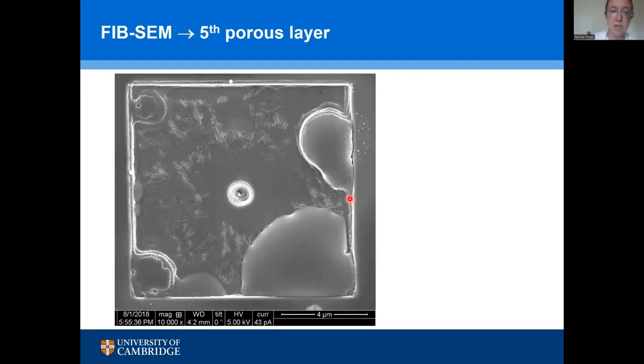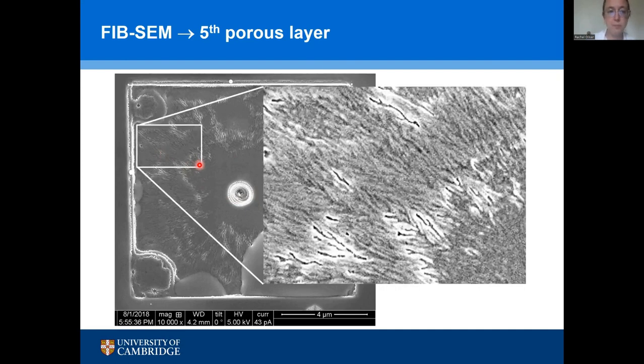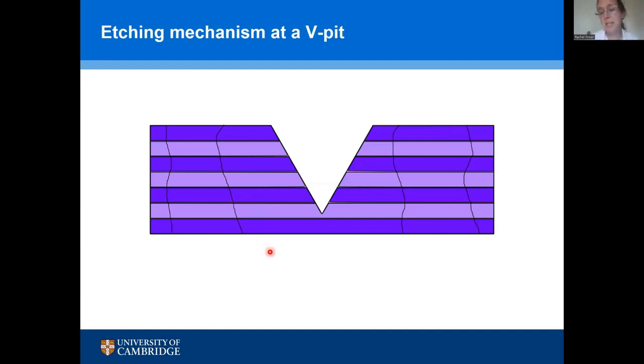But if we go down to the 5th porous layer, it looks quite different. Our milling has got a bit of a bowl shape here, so we've destroyed the middle of the porous layer before we've really accessed the edge of it. But if we look at that same region, we can now see that the porosity is all heading in one direction, aligned, emanating radially from this huge pit in the center, rather than from individual dislocation pipelines. So our etching mechanism has actually gone a bit wrong at this V pit.